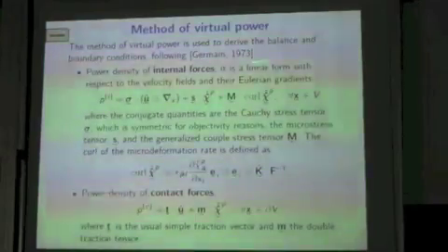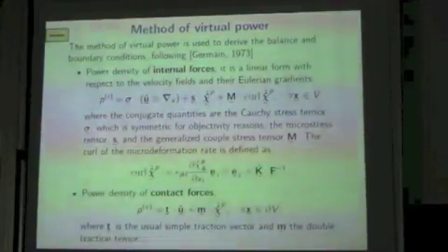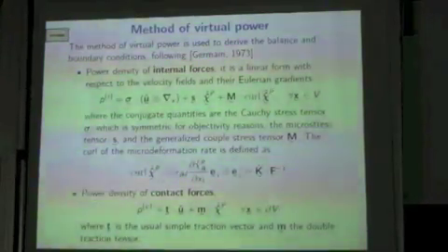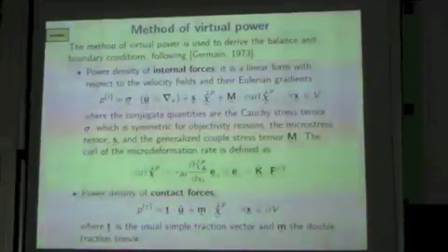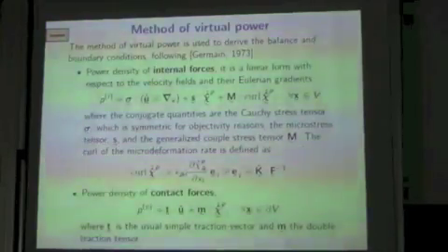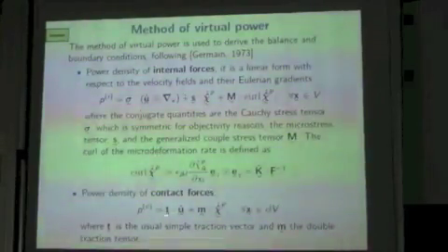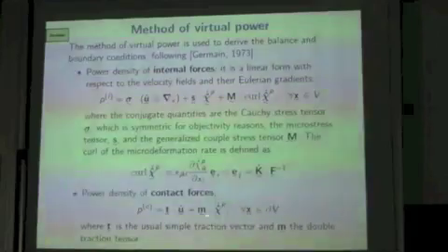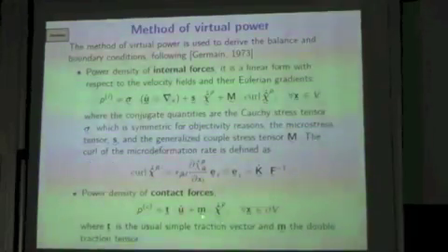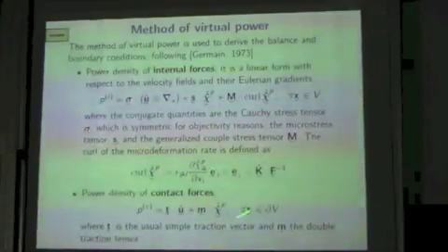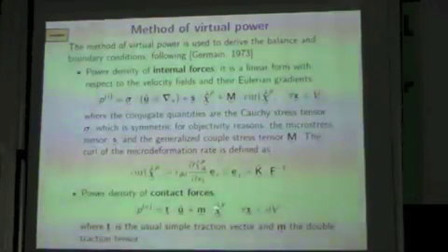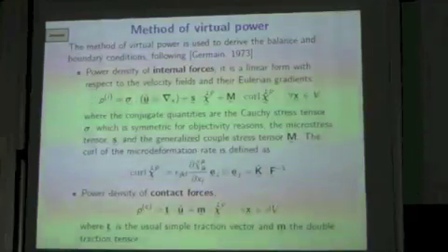And if you know that, you can compute the volume integral over a domain, and then you will see which kind of contact forces can be applied to the medium. You can apply traction forces as usual, but you can also apply double forces, a surface density of double forces, small m, which react to the micro deformation that you have here.